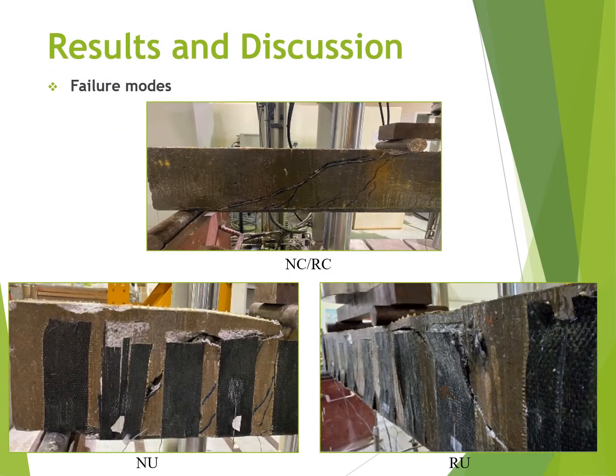Moving on to the results and discussion, starting with the failure modes. The first picture here shows the typical failure mode for the normal aggregate concrete and recycled aggregate concrete. As seen here, the beams failed by typical shear failure by the formation of a critical shear crack at an angle of 45 degrees from the horizontal. The major shear crack propagated from the supports up to the loading point, as you can see in the figure. Also, minor shear cracks were formed in the shear span.